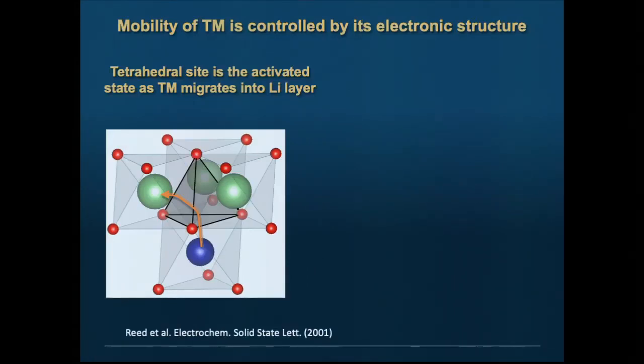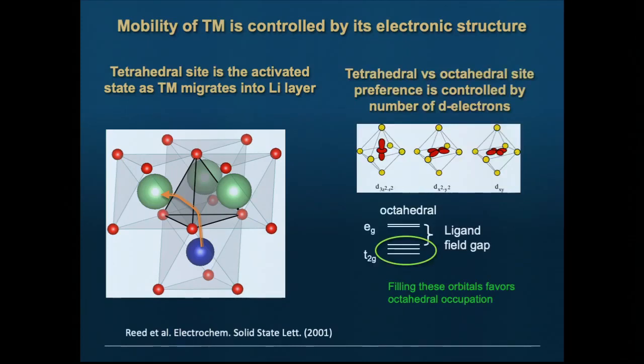So let's get to the science. Why is only cobalt, nickel, and manganese good? Well, that has to do with the mobility of these ions. It turns out that some have a much easier time to migrate from one octahedral site to another. And remember, I told you they have to go through the tetrahedral site. So it turns out the activation energy for the transition metal motion, not the lithium, depends on its electronic structure, because it depends essentially on how ambivalent it is about its coordination. It sits octahedral. If it doesn't mind being tetrahedral, then it's going to easily migrate through this, because it has to go through a tetrahedral site. Well, that depends on the electronic structure.